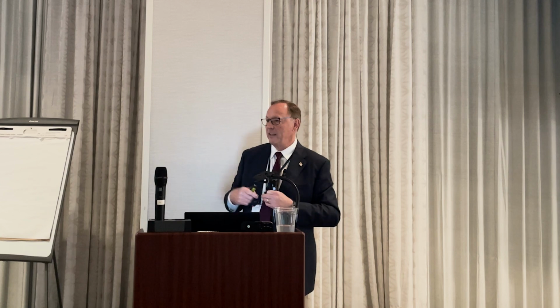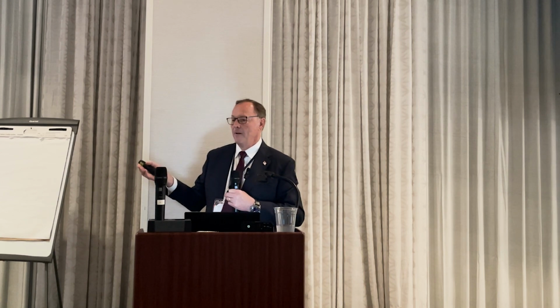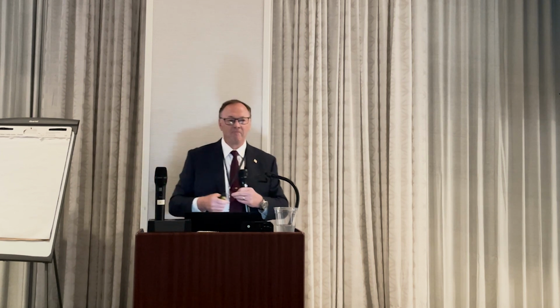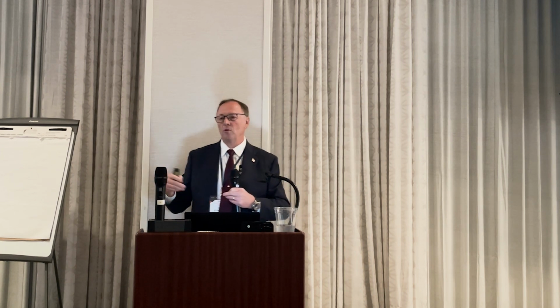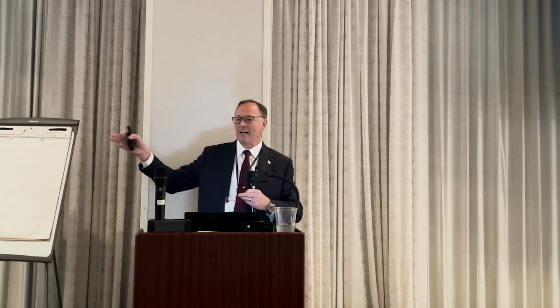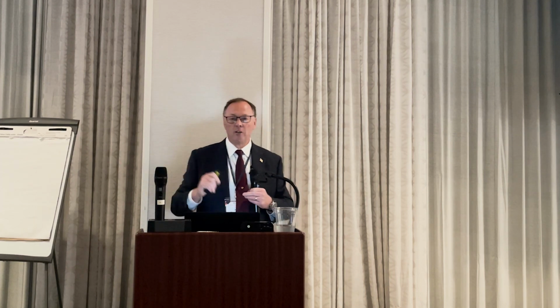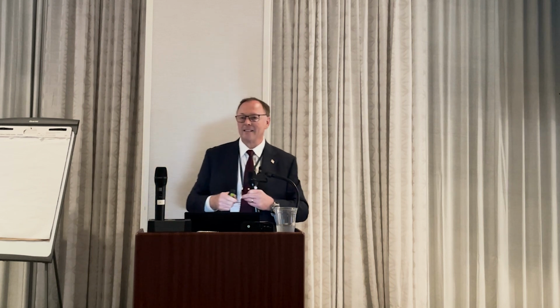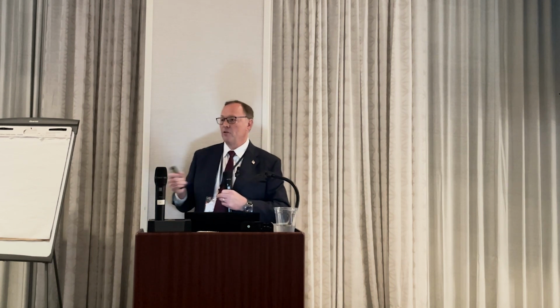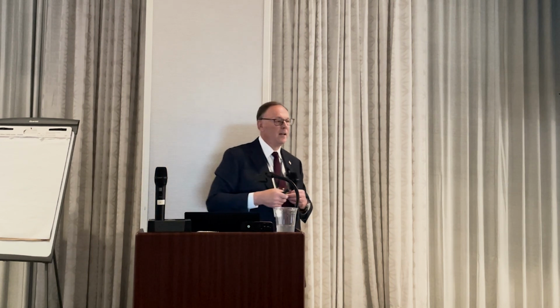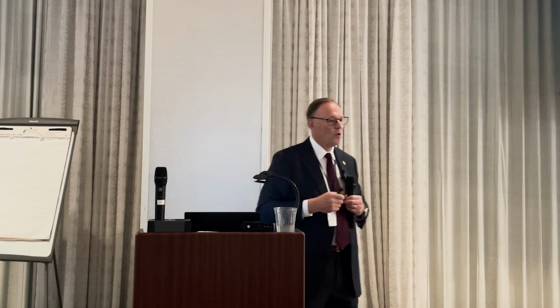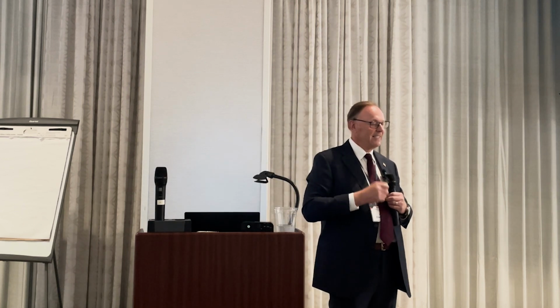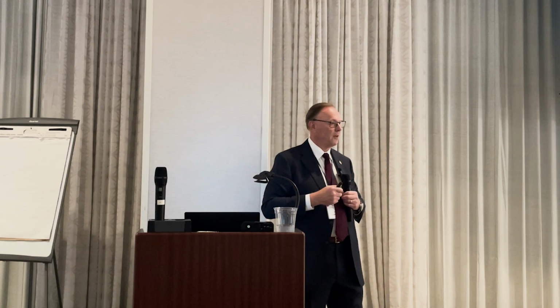Darryl showed you some of the thermal expansion coefficients of FRP compared to steel. If the systems were in steel at 200 degrees, you lay it in, typical rules: supported every 10 feet or 20 feet, have a guide every third support, and you're probably good. With FRP, it's not going to be that way. So if you're seeing leaks in your piping, in the joints, more times than not, it's an engineering problem or it's a pipe support problem.